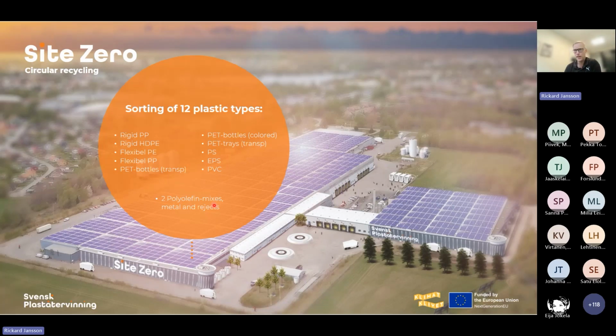So we can detect them by the sensors that we use, and we can separate them from the other mono fractions, but we can also separate them from the remaining reject that we otherwise would get them into. So in our case, we produce two different kinds of these mixes. One is mainly flexible materials, and the other one is rigid materials. And these materials we can process further into an agglomerate on site. This agglomerate we can sell for industries that use it in park bench-like structures or other wood replacement products.